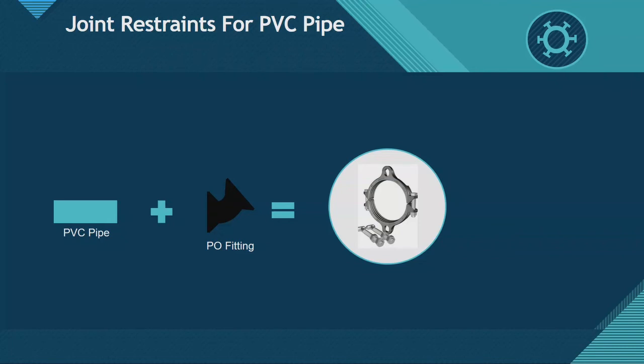If you're in 10 or 12 inch, most push-on ductile iron fittings come with 2 ears. The 10 and 12 inch serrated restraints have 4 holes for the lugs to go through. Because there's only 2 ears on the push-on fitting, you can only use 2 rods. If you're only using 2 rods, you're using half the rods that the restraint was designed for, so the pressure rating of that restraint is now cut in half. So your 235 PSI pipe to a push-on fitting with 2 rods is only rated to 110 PSI. Well, 115 plus or minus anyway. It's half the rating. So it's a very important thing to remember. 4 to 8 inch, you're okay. It's a 10 and 12 where it matters.